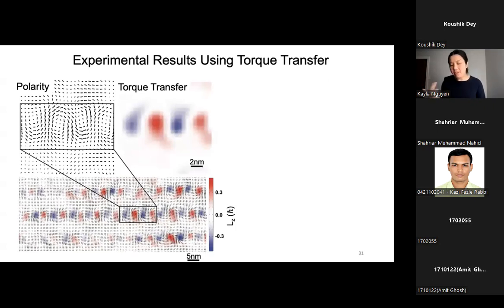Okay, so now that we have a way to look at torque transfer, one of my professors asked me, is there a way for us to extract chirality in our sample? One of the first questions is: is our sample two-dimensionally chiral or three-dimensionally chiral? Answering whether it's two-dimensionally chiral is quite easy. You have these polarization vortices, one rotating counterclockwise and one clockwise. If you take them on top of each other and rotate or translate them, no matter what you do, you can't put them directly on top of each other. They're like your hands, which never stack perfectly on top of each other. And so we know that our sample is two-dimensionally chiral.